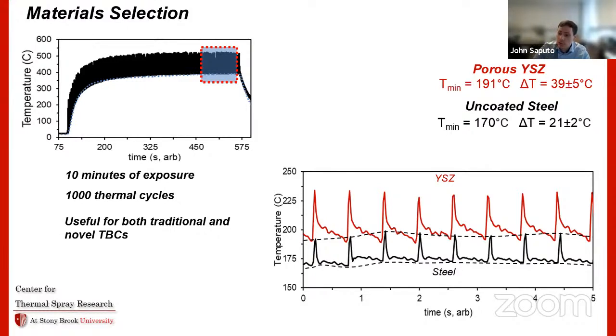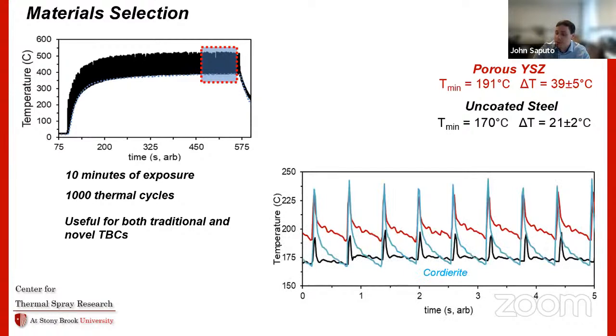So if we look at one of the most beneficial materials that we predicted from the other work that we talked about, you can see this is cordierite, that the temperature swing is about double what you see from anything else. It's about 90 degrees, and the baseline temperature is about the same as the uncoated steel, which is good. So by our lab test, this should perform well.